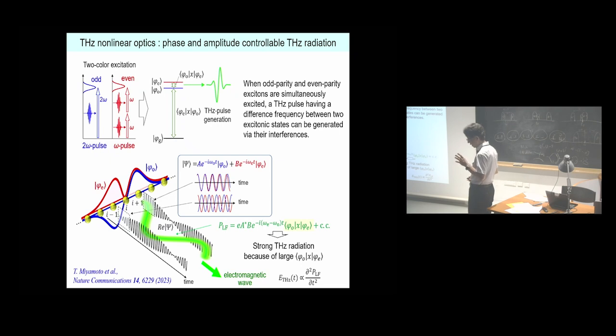Okay, using strong optical nonlinearity in 1D Mott insulators, we can demonstrate a new type of terahertz nonlinear optics, that is, phase- and amplitude-controllable terahertz radiation. The strategy of this study is summarized here. When odd parity and even parity excitons are simultaneously excited using two-color excitations resonant to the odd and even excitonic states, a terahertz pulse having the difference frequency between the two excitonic states can be generated via their interference. The magnitude of this terahertz pulse is determined by the dipole moment between these two excitonic states,